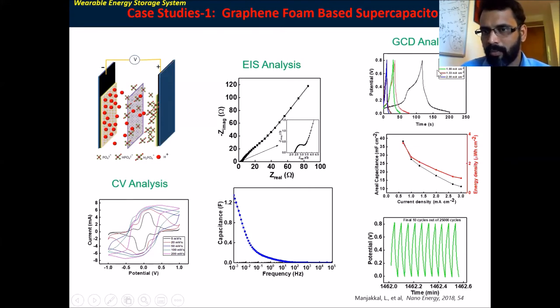As you can see here, it's not a perfect rectangular and triangle. There is a redox reaction. I observed an areal capacitance of nearly 32 millifarad per centimeter square for this device, and an energy density of 3.2 microwatt hour per centimeter square. One of the important and interesting things I found is that it operates for more than 25,000 charging discharging cycles, and you can see here the last final cycle. In this work, my colleagues Carlos Vendin and Professor Dahia and I did this work together. And here, I integrated the graphene foam with a solar cell.